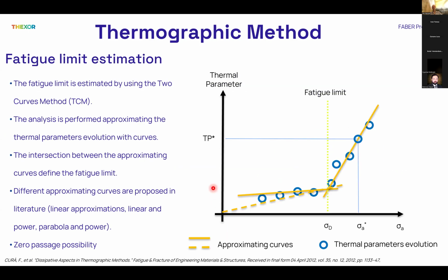So the fatigue limit is estimated by using the two curves method. This methodology is an automatic routine able to split the thermal parameters evolution based on the nature of the intrinsic dissipations, and then the fatigue limit is calculated from the intersection of approximating curves adopted to mathematically describe the thermal parameters evolution. There are several possibilities in terms of approximating curves.